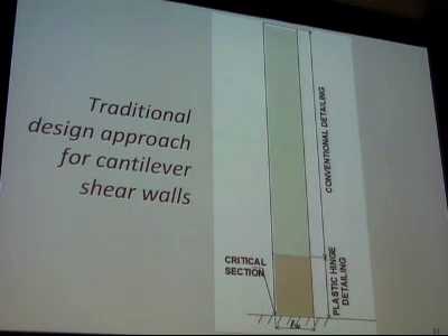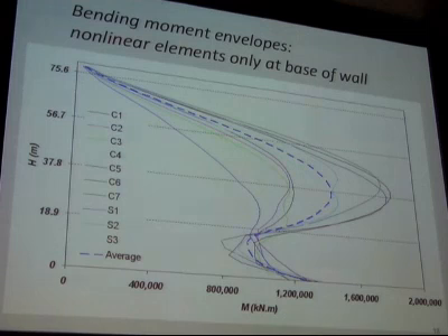The current philosophy, traditionally, has been that you provide a fuse at the bottom, you put lots of special detailing down there, and then the rest of the wall you can have essentially conventional detailing. That's been the way we've designed walls. It comes from thinking of it as a first mode pushover response, because if you have this nice ductile hinge at the bottom, the rest will be protected. And of course, we've all learned that in tall buildings, you're going to get very high higher mode bending moments near the middle of the shear wall.